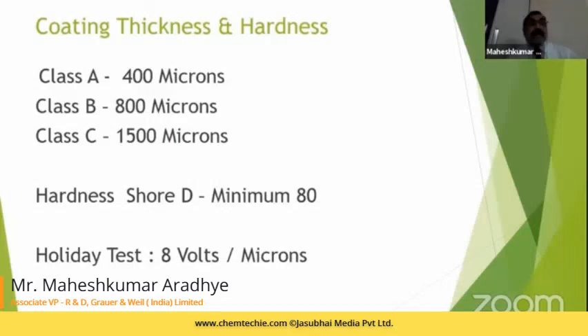Class A calls for a coating thickness of up to 400 microns. Class B calls for 800 microns, and class C calls for 1500 microns. The most critical parameter here is the hardness of the coating, which should be a minimum of 80 at that class. You can get a hardness of, say, 80 at 250 microns, but that is not acceptable. It is talking about getting the assured hardness of minimum 80 at 1500 microns, 800 microns, or 400 microns, whenever the coating is applicable to class A, B, or C.